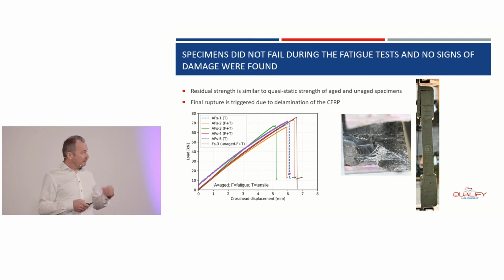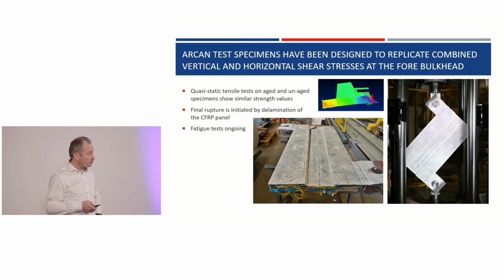And finally, if you look at the failure condition at the right, you see a crack at the interface between the composite and the adhesive, but the failure really started within the composite itself. That's why I added that photograph. So there is delamination within the composite that then, after very dynamic rupture, transferred to an interface failure in between adhesive and composite.